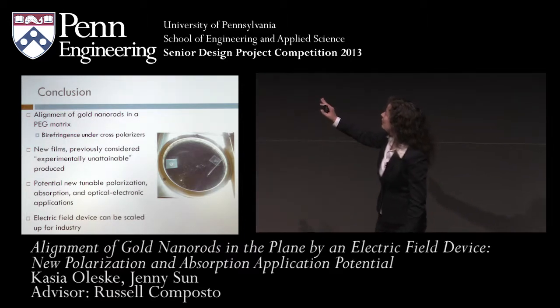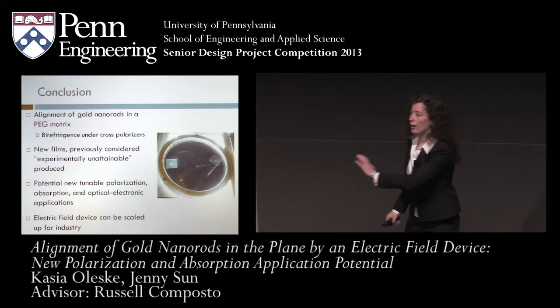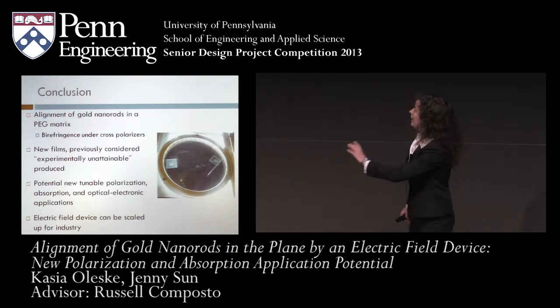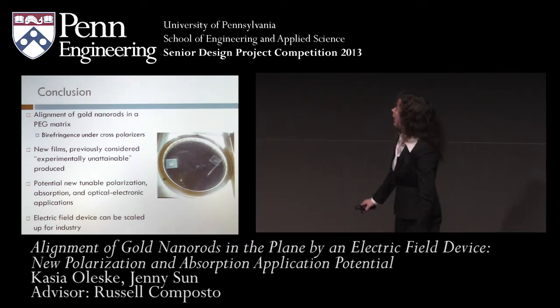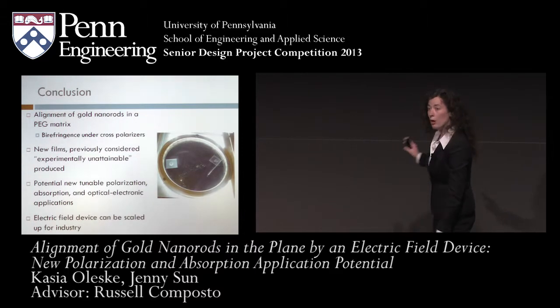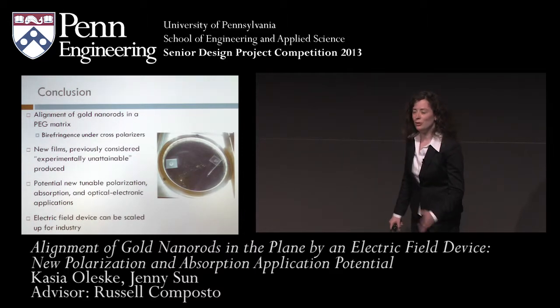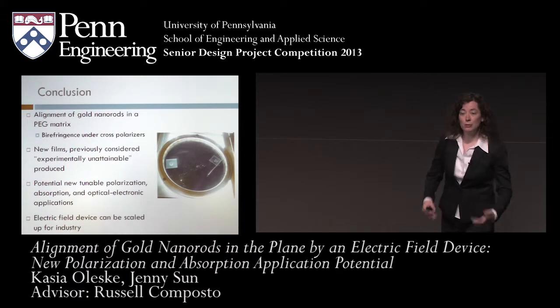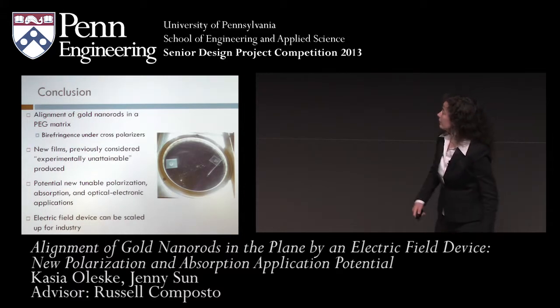So you can see in the image on the left is our oriented film, and it glows under birefringence. And the control sample is on the right with no electric field, and it has minimal to no birefringence, which means we truly did get alignment.